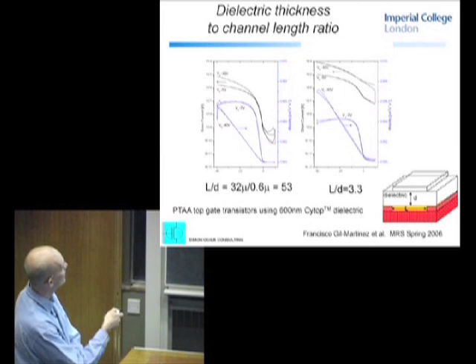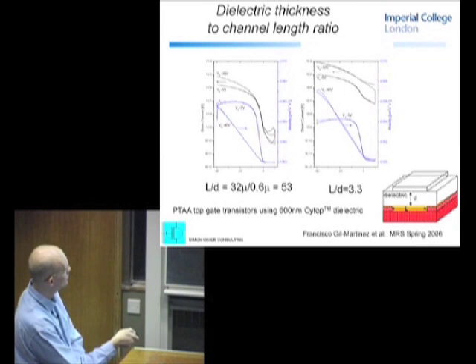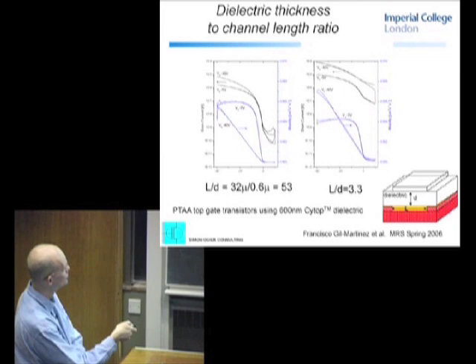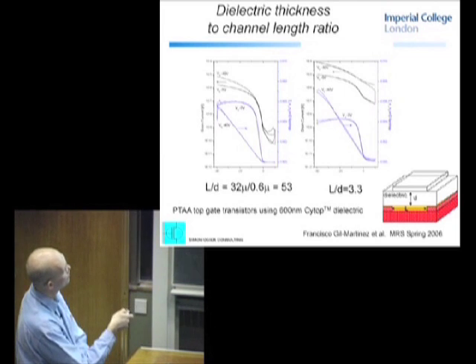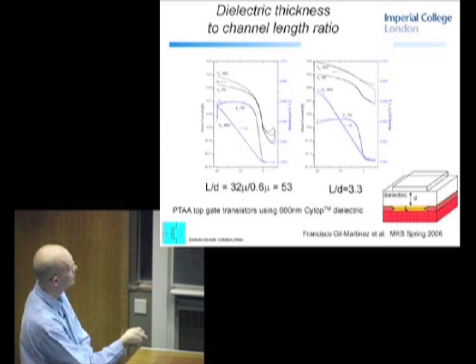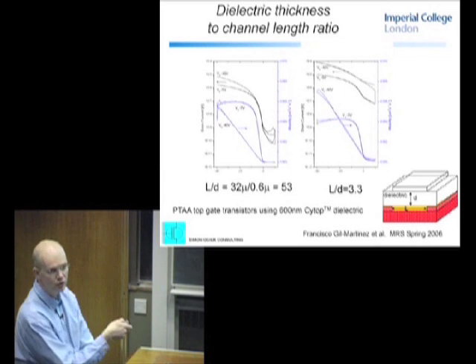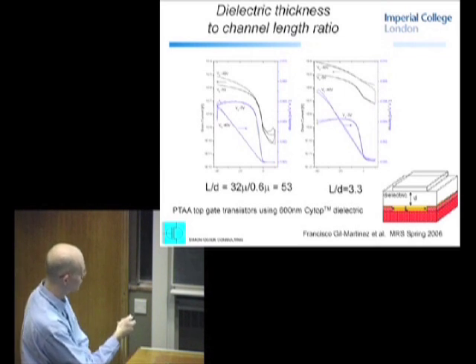So in this case, you have one device with a longer channel-to-thickness ratio, and in this case the L/d is much shorter, then the sub-threshold region is not so good when you've got too thick a dielectric with respect to the channel length. It's harder to accumulate the charge, it doesn't switch on, the sub-threshold region is not so good.